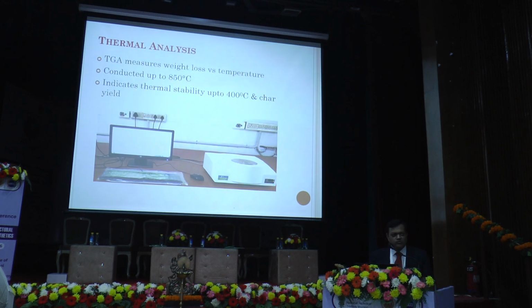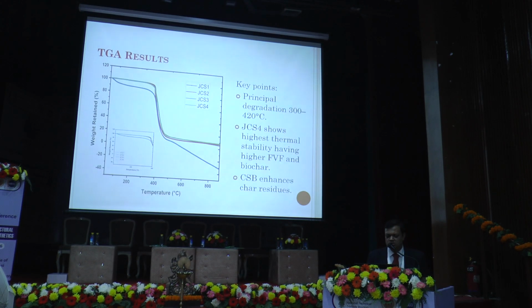And we went for thermal analysis, that is TGA, up to 850 degrees Celsius, and the graphs obtained were like this. You can see up to 400 degrees Celsius the principal degradation happened, and JCS4 shows the highest thermal stability, having higher fiber volume fraction and biochar content.